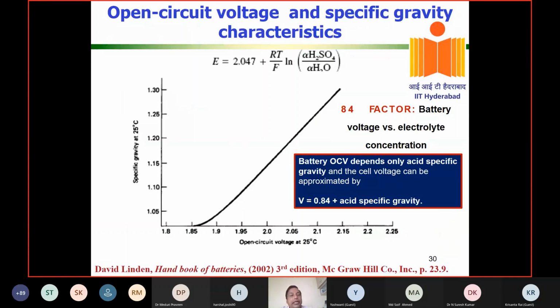As I told you, how can we get the potential of this lead acid cell? You already know that the concentration changes. If you know the concentration of the sulfuric acid, you know the standard electric potential by the Nernst equation: E equals E naught, which is 2.047, plus RT by F ln of the activity of sulfuric acid to water. So if you know, you can easily get the EMF. A very simple derivation has been obtained for the lead acid cell: the EMF equals 0.84 plus the acid specific gravity. If it is a flooded cell, you can easily determine what could be the voltage of the cell by knowing the specific gravity.